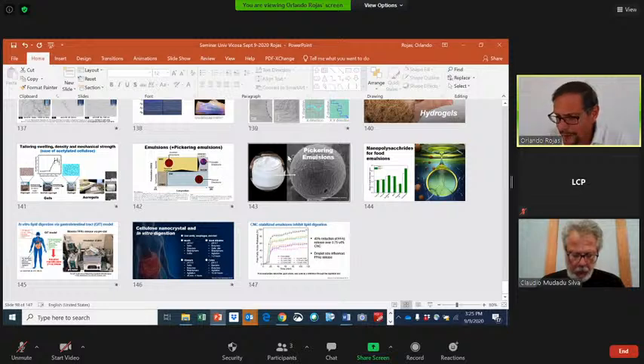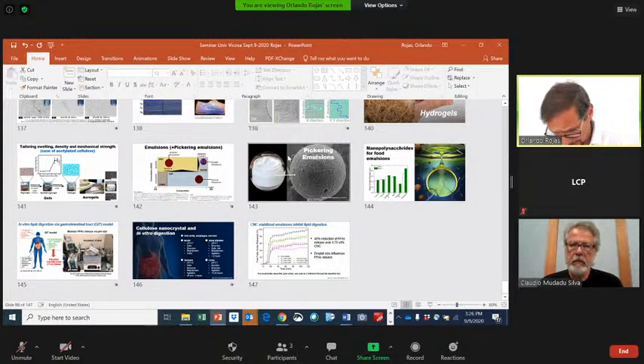But about the hydrophobization, of course, the idea here is probably to first coat the nanocellulose, taking advantage of the affinity of cellulose with cellulose, meaning nanocellulose with fibers. It makes a very strong binding, and then do the hydrophobization after the material has been coated. And for that, I think the preferred route probably is that one. That is to have the coating first and then using UV click or other procedures, including vapor deposition, to have the coating on the already installed nanocellulose that can be acting as a barrier, but also as a water repellent material.